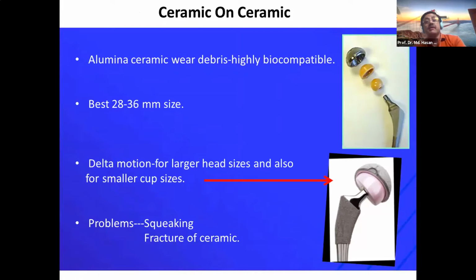And alumina ceramic wear debris is highly biocompatible. Now an implant of choice is with a ceramic head and ceramic bearing, that is the alumina ceramic, and best is 28 to 36 millimeter size. Okay, and it has a lower level of osteolytic cytokines compared to ultra high molecular weight polyethylene and is less cytotoxic than the metallic debris. And sometimes the Delta Motion cup is needed for larger head size and also for a smaller cup size. And there are also some disadvantages of ceramic, like they produce a sound which is called squeaking, and sometimes a chip fracture of the ceramic.